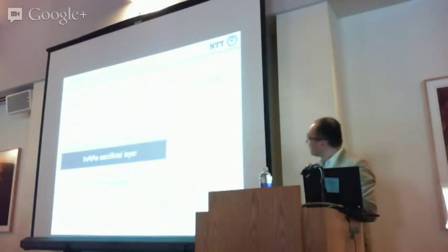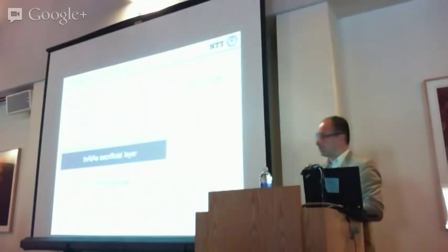So let me explain the fabrication process. First, we grow the active region on a semi-insulating indium phosphide substrate. And in this case, we use an InGaAs sacrificial layer to reduce the leakage current. Then we regrow the indium phosphide around the active region. Then we implant the silicon ion under these conditions. The activation temperature is 650 degrees.